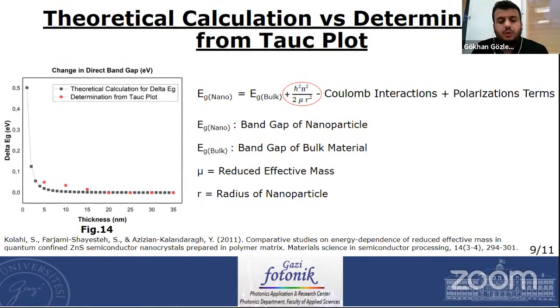Change in the band gap according to the radius of the nanoparticle can be calculated. The formula is seen on the right side of the slide. As you see, delta band gap is inversely proportional to the square of the radius of the nanoparticle. We calculated the radius of the nanoparticle from 1 nanometer to 35 nanometers, and delta Eg is 0 after 10 nanometers. Also, as you see, the quantum confinement effect increases drastically below 5 nanometers.